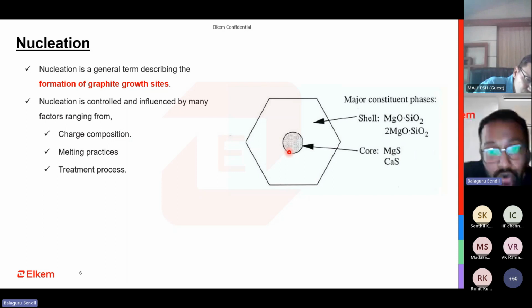Again, how do you do the treatment process in the case of ductile iron? You are doing a nodularization process. Your base metal has these nucleating sites. If you're holding it for long in the furnace, these will get degenerated. Again, when you're doing the treatment process, as we saw in the first couple of slides, after treatment the microstructure doesn't look very great. So it is very important what this treatment process is, and how you are going to introduce this nodularizer is very important.